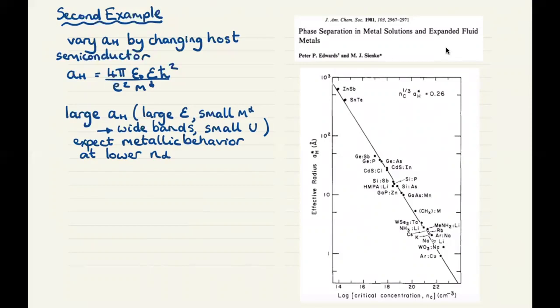So here's a collection of the measured critical concentration, the concentration at which the system makes a transition between the insulator at low concentration and the metal at high concentration, as a function of the effective radius. So a few things to notice here. The first thing is that the plot of the hydrogenic radius versus the log of the critical concentration to the transition gives us a straight line.